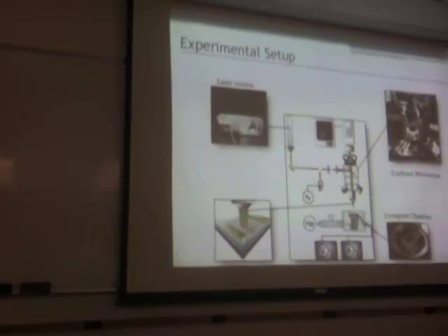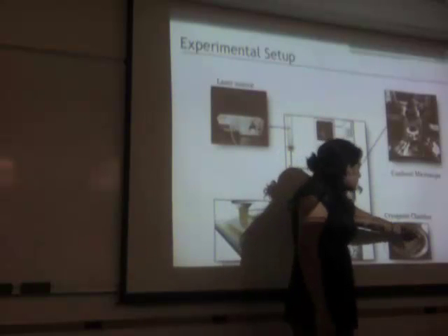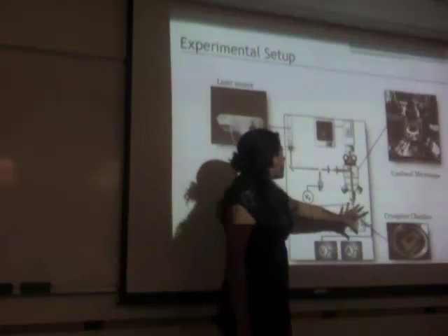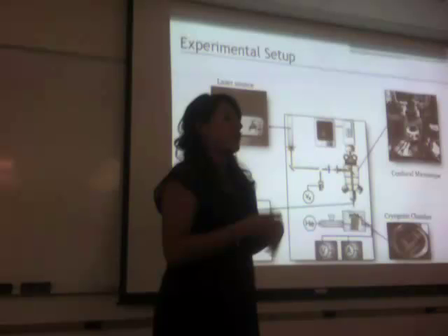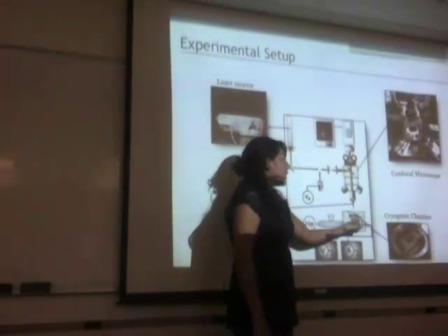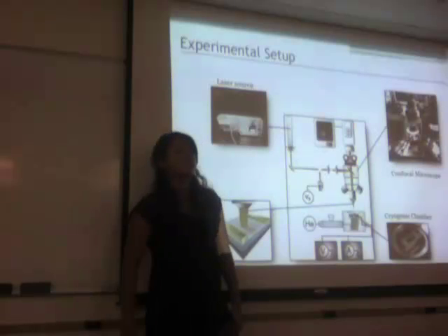And this was actually the experimental setup that I worked with. We had the bismuth selenide on a substrate in a chip holder in this chamber, which we pumped down with a turbo pump to vacuum conditions. We had liquid helium feeding into a capillary that was in direct thermal contact with the chip holder, so that we attained temperatures of about 4 Kelvin in our experiments.